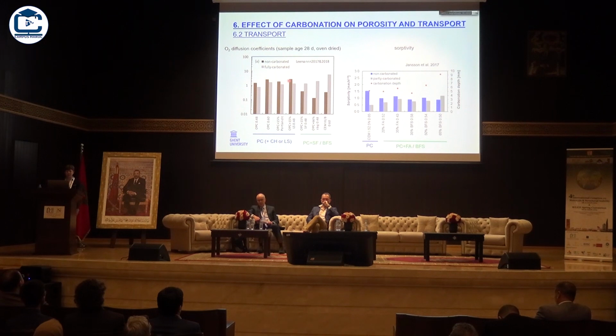What about transport properties? Well, here it is clear. The black bars are non-carbonated, grey bars fully carbonated. For Portland cement, possibly with addition of limestone, carbonation leads to a small reduction in the diffusion coefficients, whereas if you have mixes with silica fume or slag, it might be an increase. But since you start at a lower value, the final value may not be all that different. Similar for the sorptivity, non-carbonated and then partly carbonated, a decrease for mixes with Portland cement or low amounts of fly ash and blast furnace slag, but an increase if you have, for instance, 50% slag.